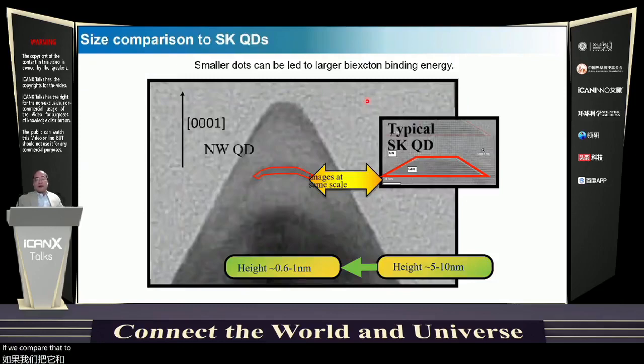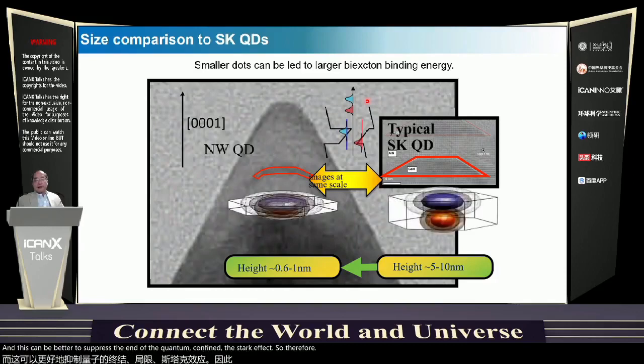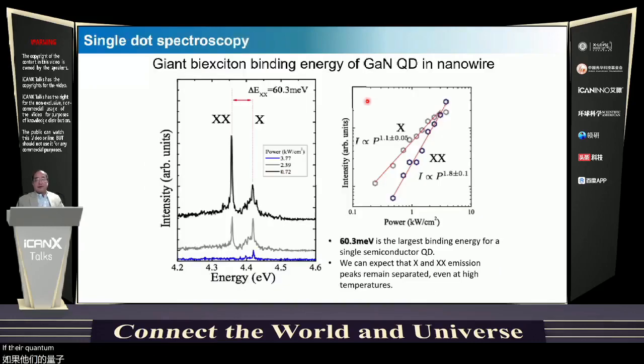If we compare the two kinds of dots, the nanowire quantum dot and the SK quantum dot, we see a clear difference. The height is much smaller in the nanowire quantum dot structures. This leads to suppression of the quantum confined Stark effect, so the oscillator strength can be much increased compared to SK quantum dot structures. In single dot spectroscopy, we achieved a biexciton binding energy of 60.3 milli-electron volt. The biexciton peak is located at the lower energy side compared to the exciton peak, which means the biexciton binding energy is positive.